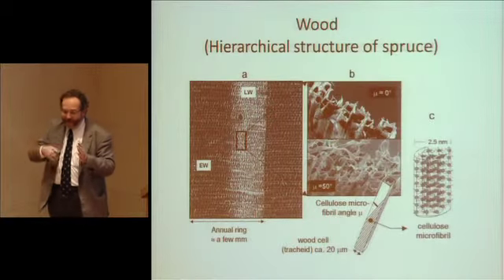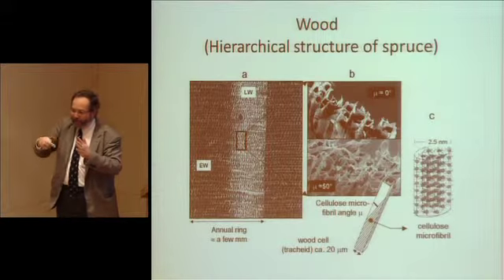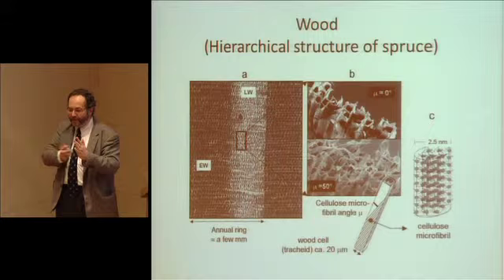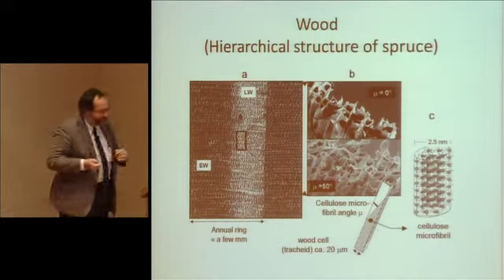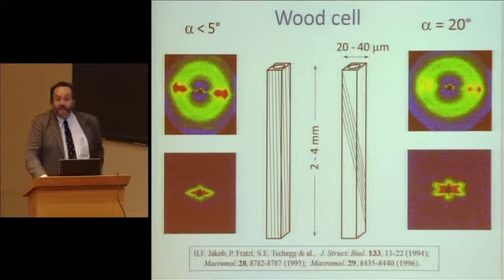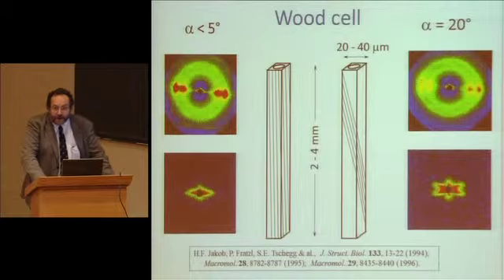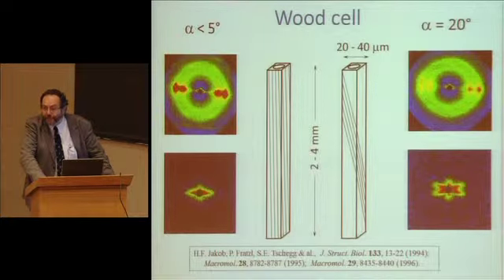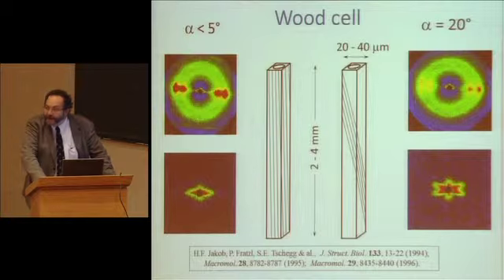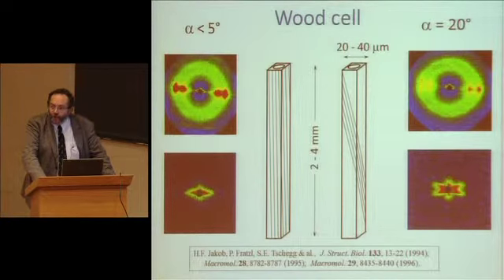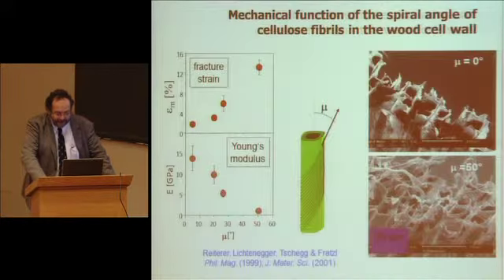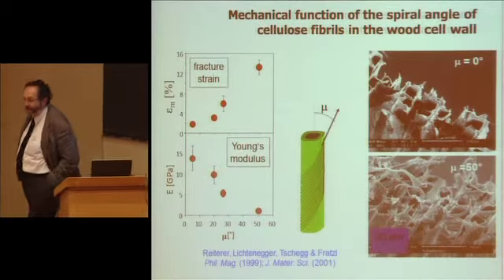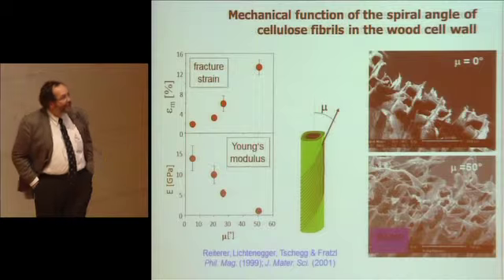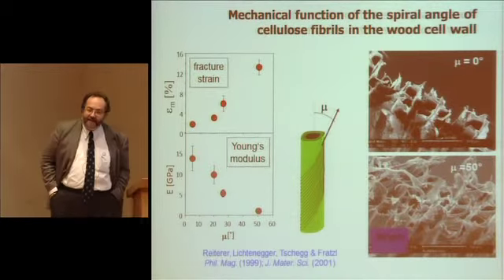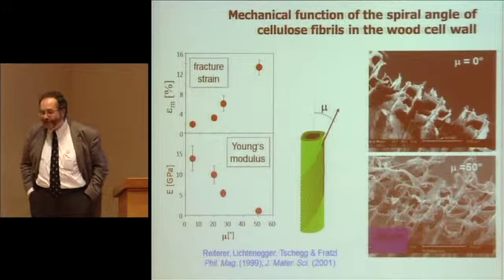So if you want wood that's very flexible, if you look at the stress axis, you need to have something that's perpendicular to that. And if you want wood that's very rigid, you're going to try to wind that along the axis. It's something that can be measured. There have been experiments carried out by an Austrian team consisting of X-ray diffraction, essentially using the same experimental tools as what is used in metallurgy. You can measure the crystalline orientation of the cellulose fibrils, and you can actually take each of these little cells and measure the elasticity modulus and deformability. Easier said than done.